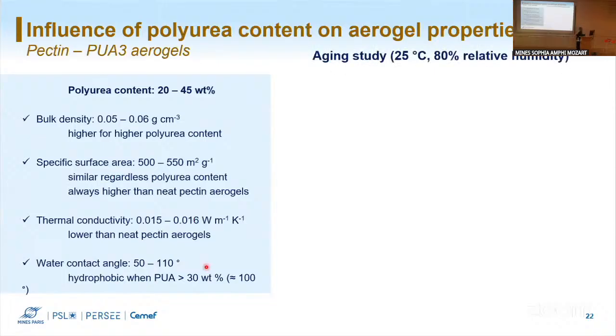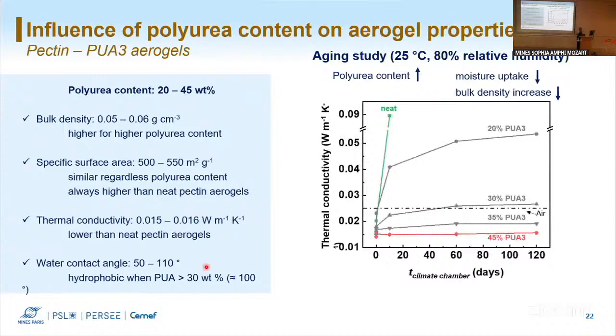We did aging studies in the same conditions as before, at 25 degrees and 80% relative humidity. When polyurea content was increasing, then moisture uptake was decreasing and bulk density increase was lower. For the thermal conductivity, we can see that when we have 35% polyurea in our material, then we still have, after 120 days, superinsulating properties, but only for 45% of polyurea, complete stability was reached.